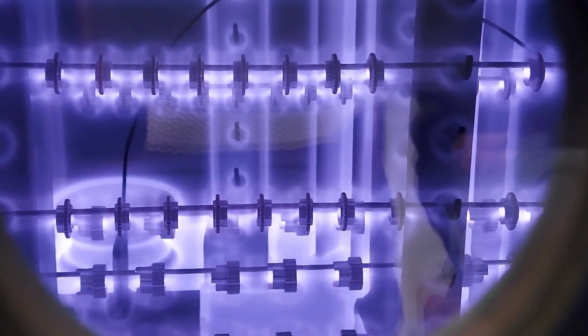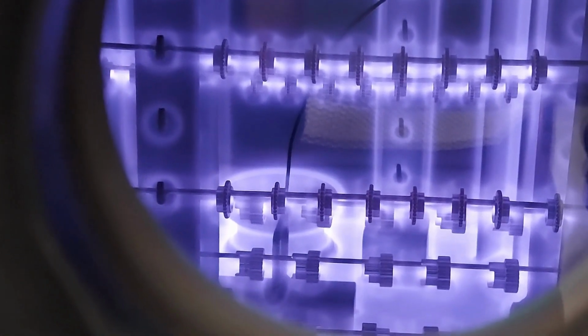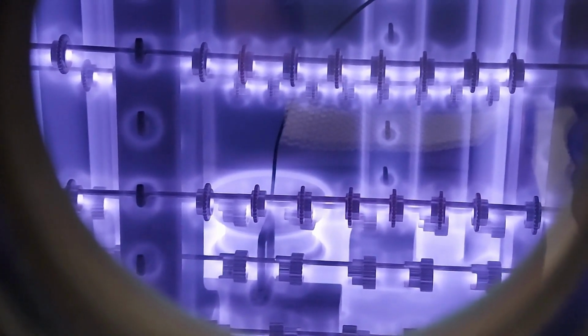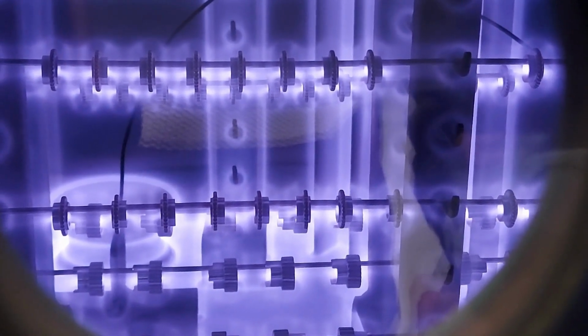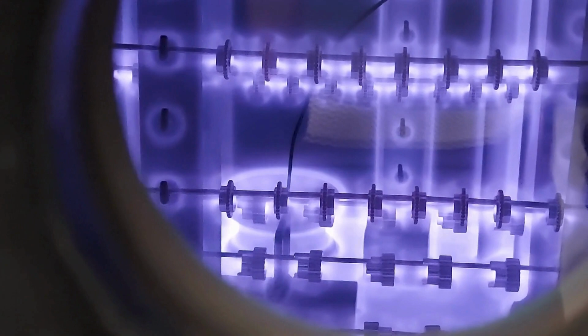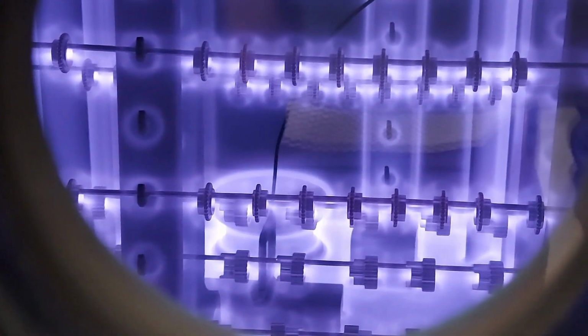As a conclusion, we can say that ion nitriding of steel grade AISI 4142 is very suitable, achieving great surface hardness and a good diffusion depth, even when it is required to be smaller than what is normal for this steel. Most importantly, even though the gears were very small, excellent uniformity of the diffusion layer has been achieved as on top of the teeth, as between them, and it is not a problem for ion nitriding.